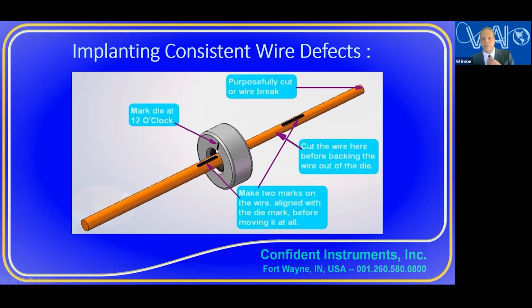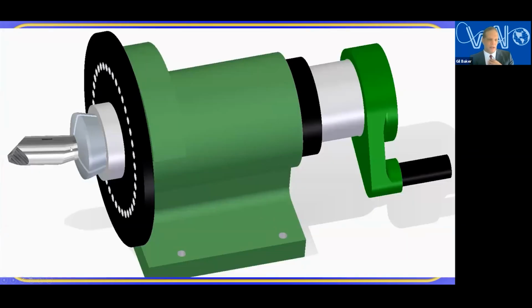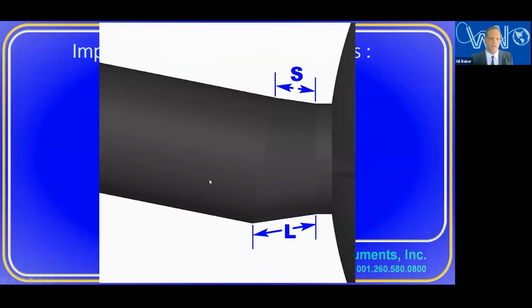Of course, I would mark everything relative to the die so you're able to orient yourself. And then here's an example of a wire with the mark where it was relative to the die. What you're going to do is measure the S and the L, L being the longest length in the deformation zone and S being the shortest length. I put it in a collet because it's really an exact measurement, especially if the cast is not in the same plane as the 12 o'clock of the die. That's also discussed in the article. So here again is the S and the L, and there's an equation in the article.